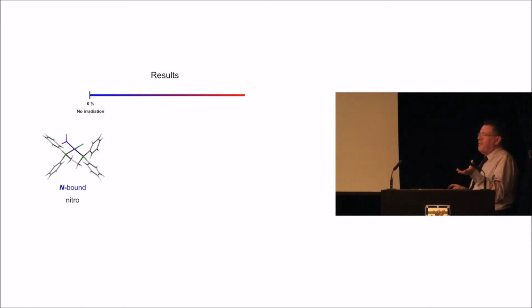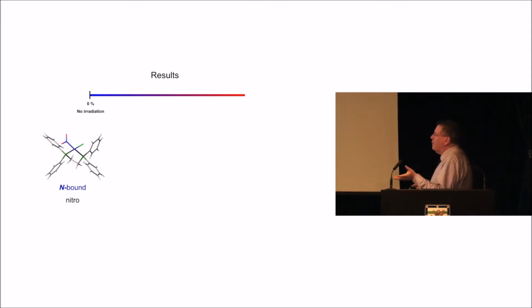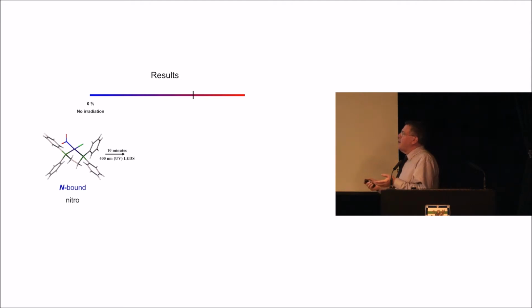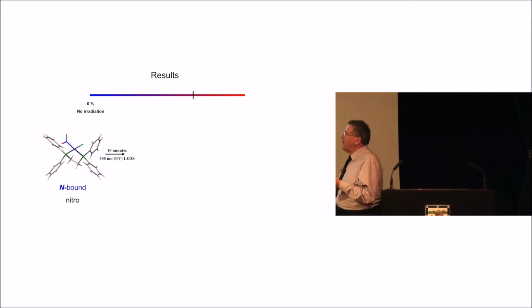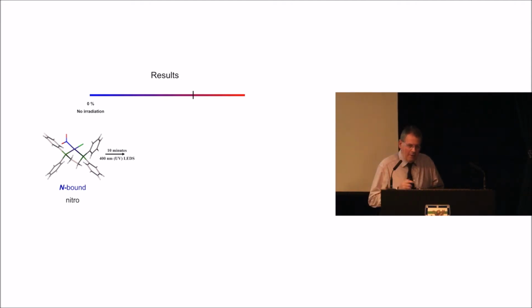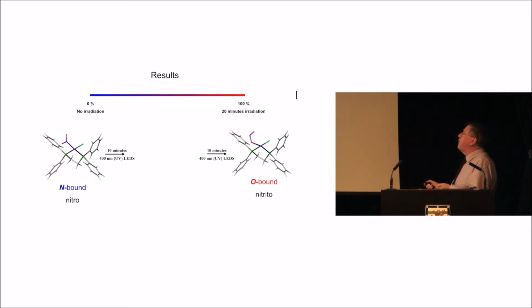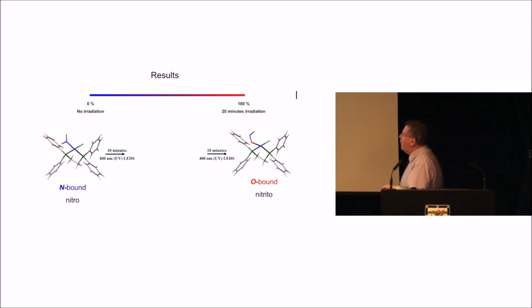So also, how fast does it go? Within the single crystal, you start with your N-bound. In about 10 minutes, you get 50% conversion. So here you have your disordered model. And in 20 minutes, you go through, in the single crystal, to the O-bound form.